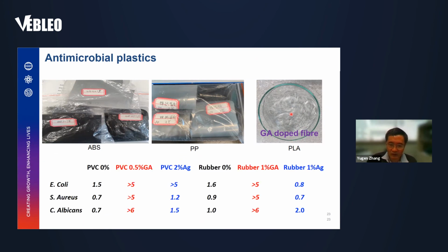And we also tried to compare with one of the most commonly used in the market, the silver-based antimicrobial ingredients. And you can see here for PVC, 0.5% of our materials demonstrate excellent antimicrobial properties. But for the PVC with 2% of silver-based materials, their efficacy is much less or worse than our materials. And similarly for the rubber-based plastics, our materials also demonstrate much better performance as compared to the silver-based one.